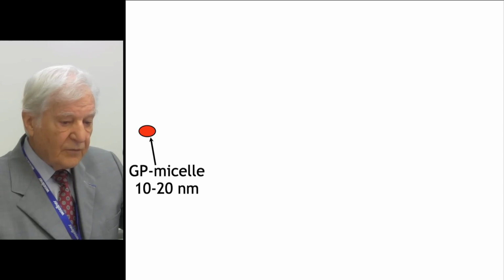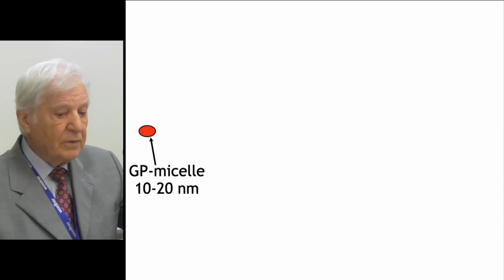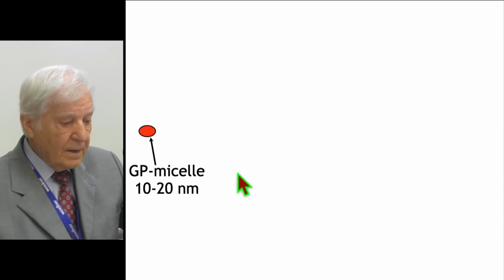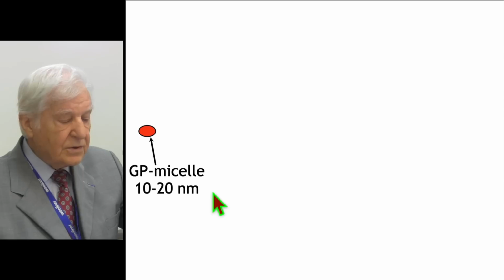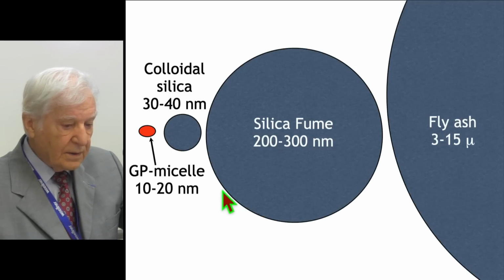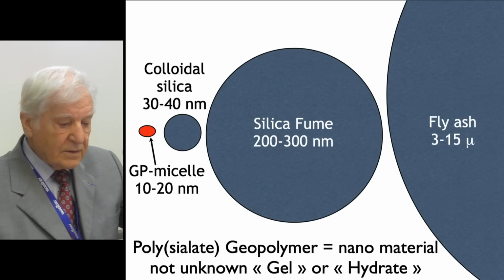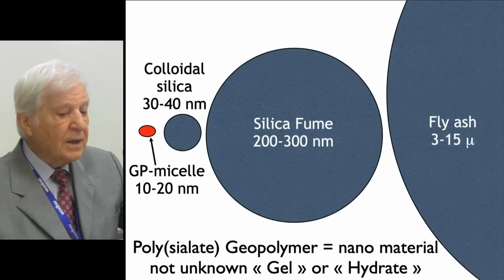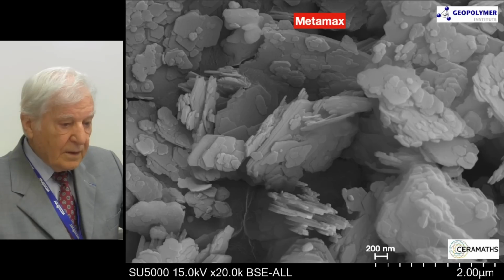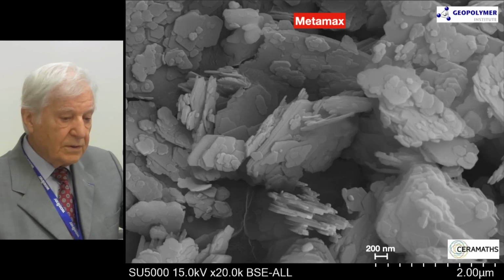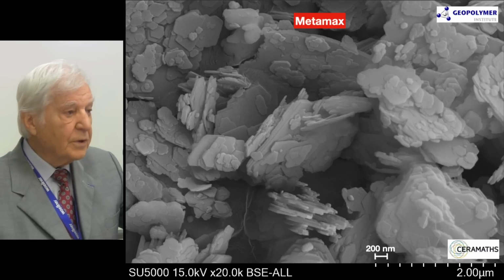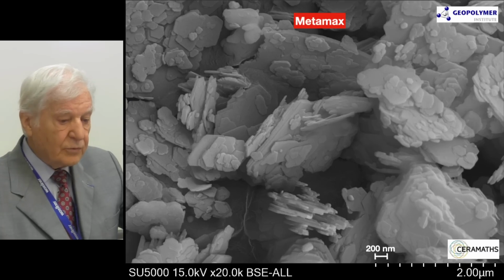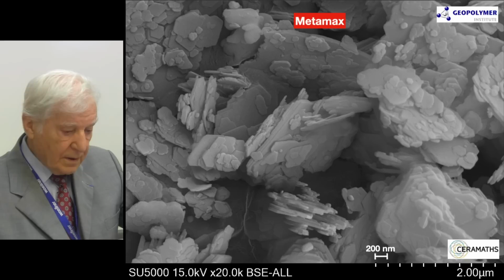The geopolymer matrix is made of nano and submicron ellipsoidal particulates, which we call geopolymer micelles. The figure shows the very small dimensions of the geopolymer nanoparticulates, geopolymer micelles, when compared to other spherical structures like colloidal silicas, silica fume, or fly ash. Geopolymer is a nanomaterial, a polymer. It is not a gel. The starting metakaolin in the Arizona State University experiment was the commercial product Metamax, with its typical tabular macrostructure for metakaolin. The scale bar is 200 nanometers.